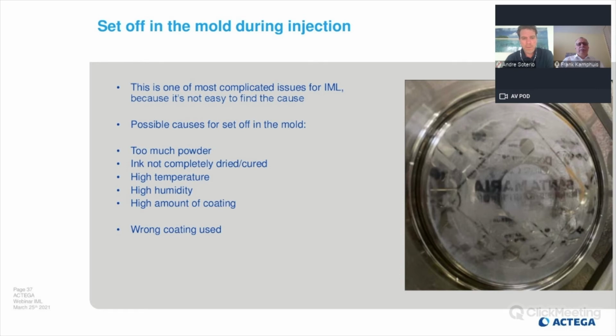And besides using too much powder, the most common mistake is to use a wrong coating. So if you are using a standard coating for IML, even if it works in the beginning, it's only a question of time until you get big problems with these technical topics. So if you find some problems in your production, please ask us. We have a solution for this problem.